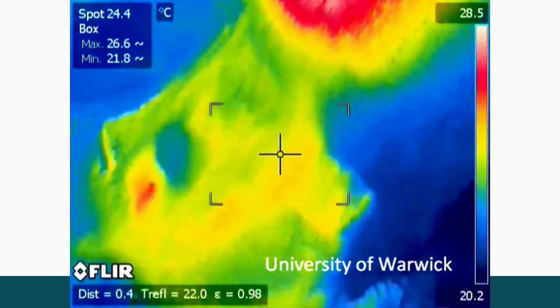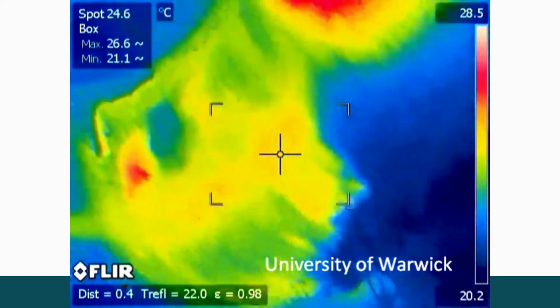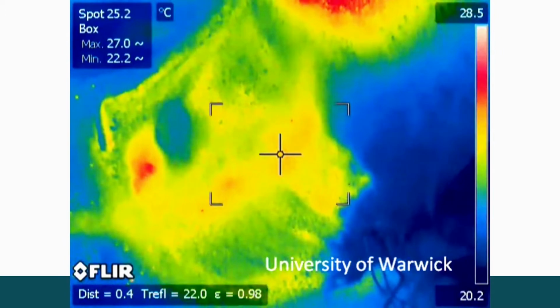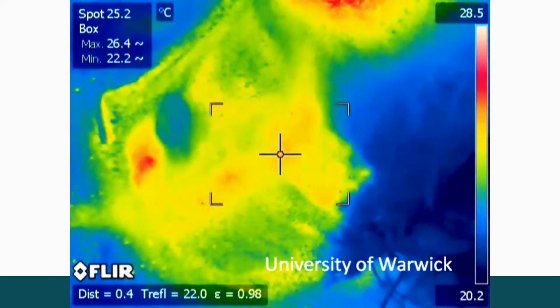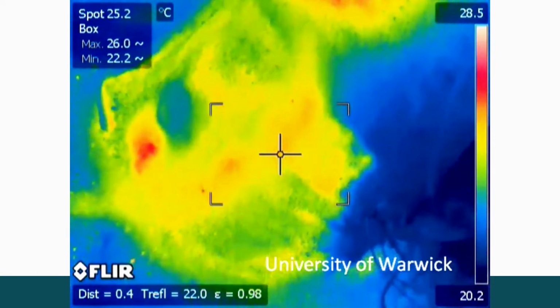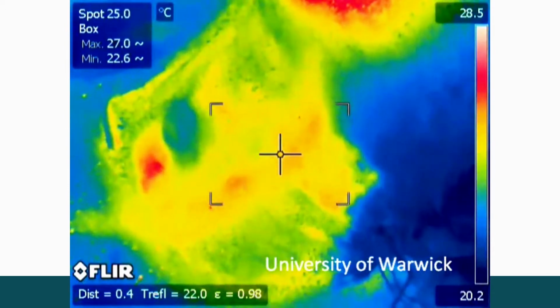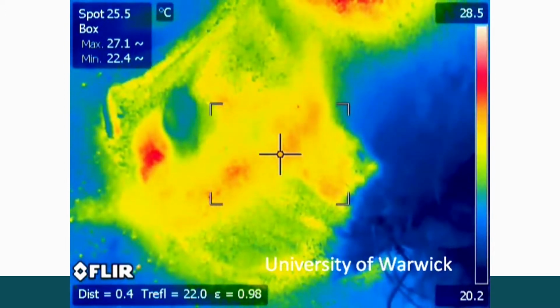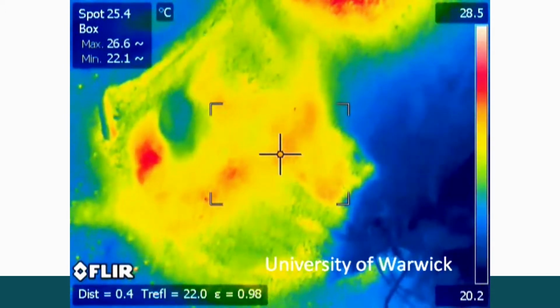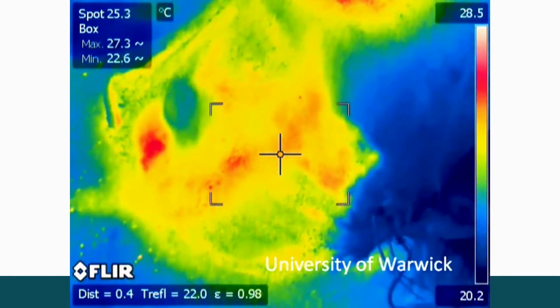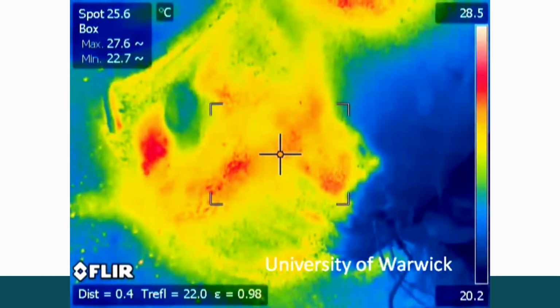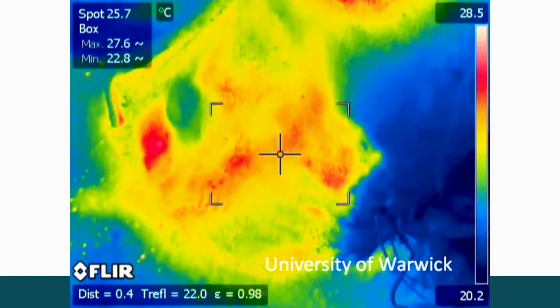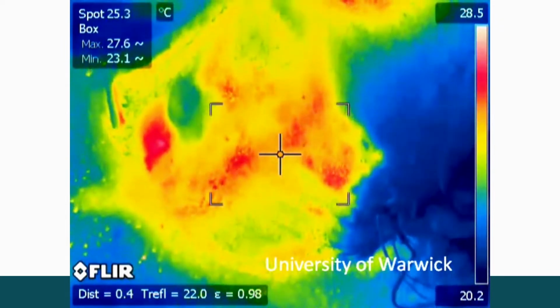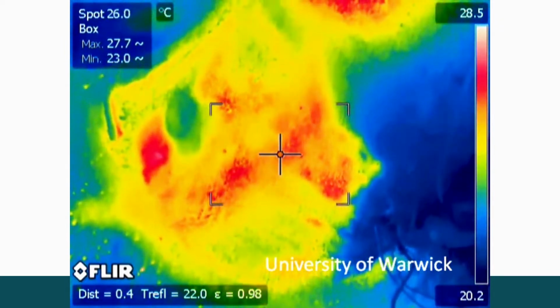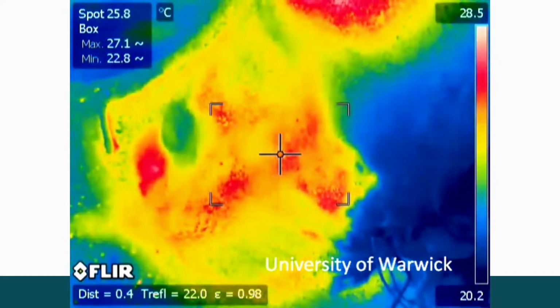And here it is after spraying. At the end of the spraying, I think they just turned off the accelerator a second before the concrete, and they got a little patch of unaccelerated concrete, which is showing up blue, that little round blue bit in the middle. And that's not just unaccelerated, it's retarded, so that's not going off for hours. But it's probably very superficial, I wouldn't worry about it. And it's down there, so it's not going to fall anywhere.